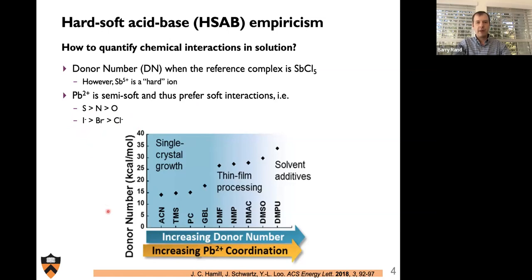And work from Lin Liu and Jeff Schwartz and Clay Hamill, who I believe also gave a talk in this seminar series maybe some year ago or more, showed work whereby increasing donor number generally led to a change of the expectation for these methyl ammonium iodide and lead iodide in solution, whereby low donor number solvents, things like acetonitrile or propylene carbonate or gamma butyrolactone, would lead to single crystal growth, basically because they didn't coordinate very strongly with the lead iodide. So the lead iodide system would come out of solution and crystallize.